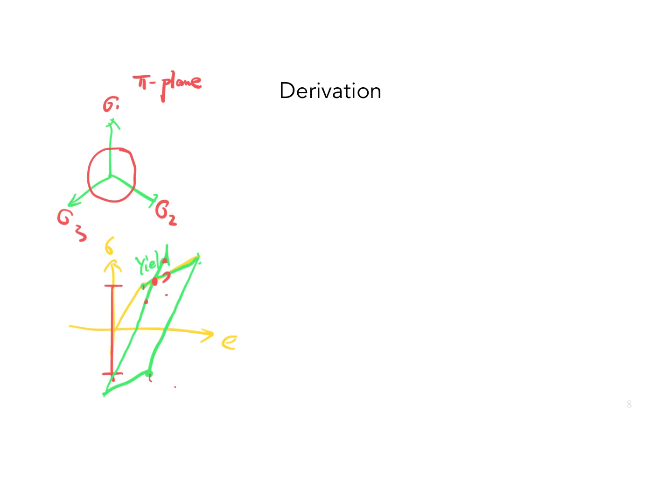But for a common material, the first assumption that people often make is that it would be isotropic hardening. What is isotropic hardening is very simple geometrically. If I have a circle here and I consider the radius, isotropic hardening basically indicates that the new radius is bigger than the original one, and I have a yield surface like this. It becomes bigger, and that is called hardening.